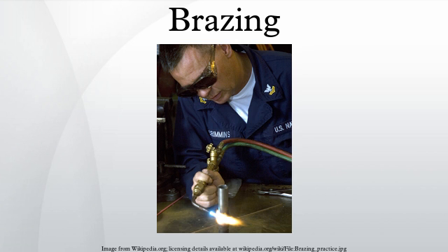For example, some alloys dissolve both silver and copper. Dissolved silver lowers their melting point and increases fluidity, copper has the opposite effect. The melting point change can be exploited. As the remelt temperature can be increased by enriching the alloy with dissolved base metal, step brazing using the same braze can be possible. Alloys that do not significantly attack the base metals are more suitable for brazing thin sections. Non-homogeneous microstructure of the braze may cause non-uniform melting and localized erosions of the base metal. Wetting of base metals can be improved by adding a suitable metal to the alloy.